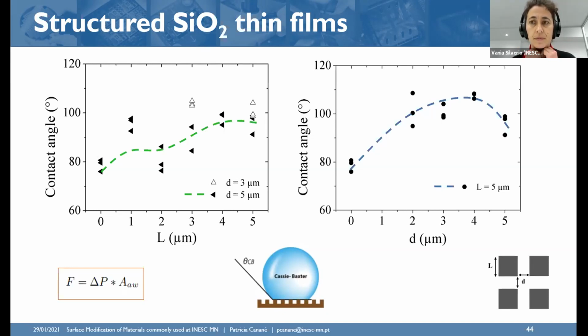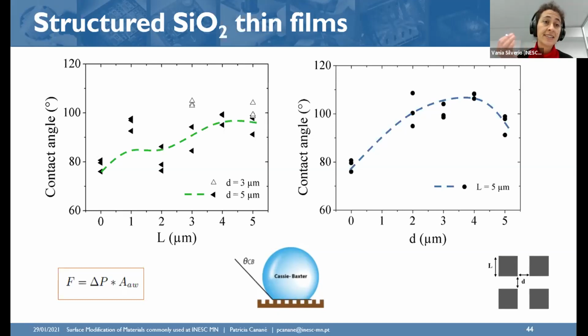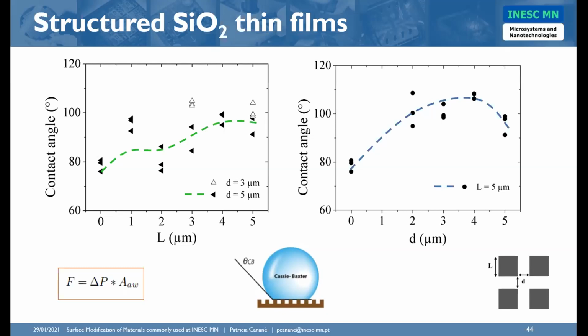Okay, very small structures, and they are very close to each other, right? Yes. It will be a problem also when I'm peeling off my PDMS because of the accumulation of polymer in dead parts. The process will help me to keep my molds intact for more time. Yeah, true. Also, because the peeling is facilitated, the adhesion forces are a lot less, so they are less prone to bring the SU8 attached to the PDMS. Yes, the difference is really night and day when peeling off PDMS from a substrate without and with silanization. No comparison between them.